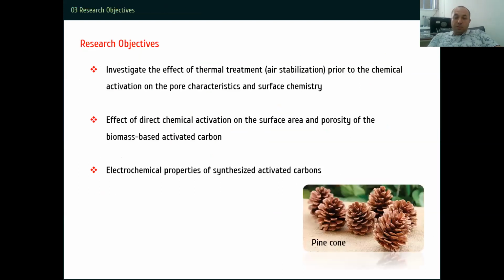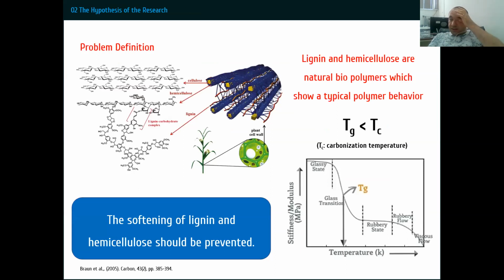But we have the problem here. As I said before, the biomass is composed of mostly lignin, cellulose, and hemicellulose, and they all have different thermal characteristics. Lignin and hemicellulose are natural biopolymers, and they show classic polymer behavior with the increasing temperature. After the glass state, they turn into wax-like materials, and the wax state limits the formation of ordered porous carbon structure. Therefore, the softening of lignin and hemicellulose should be prevented. The glass transition temperature, Tg, can be increased by controlling the heating rate.